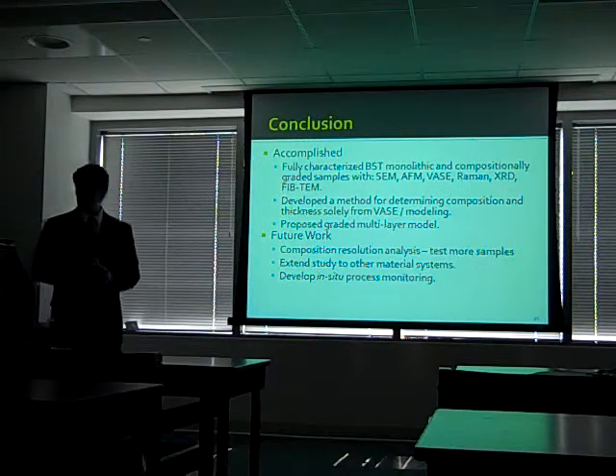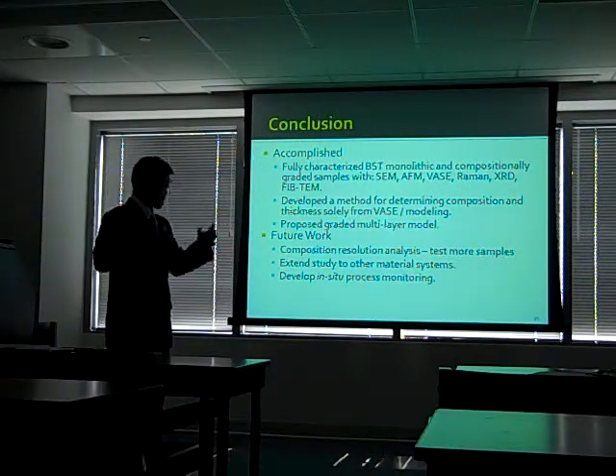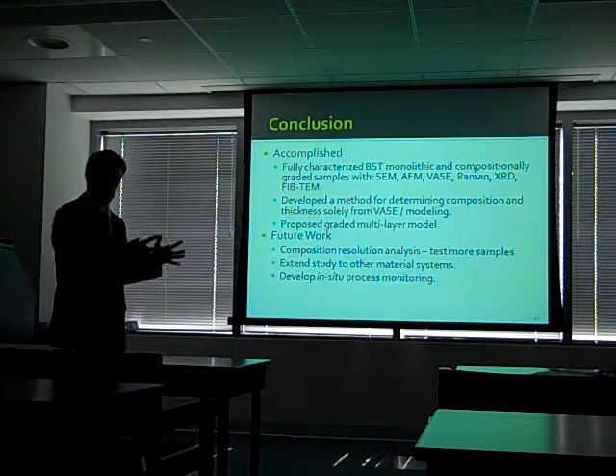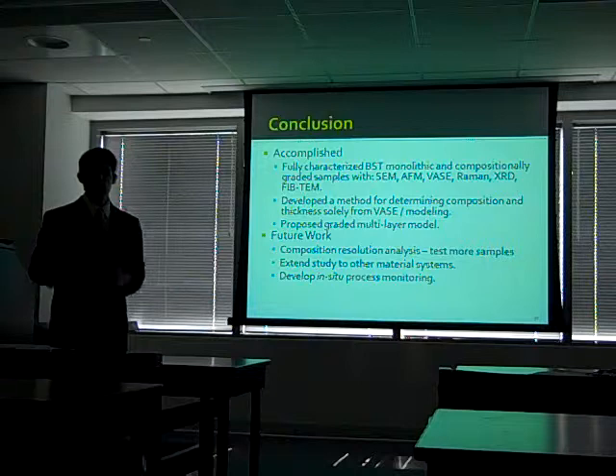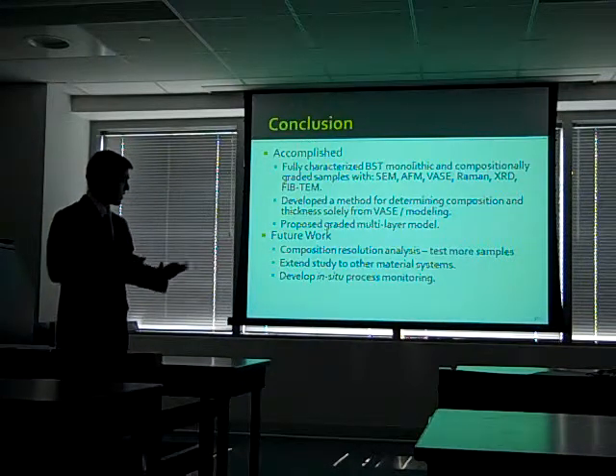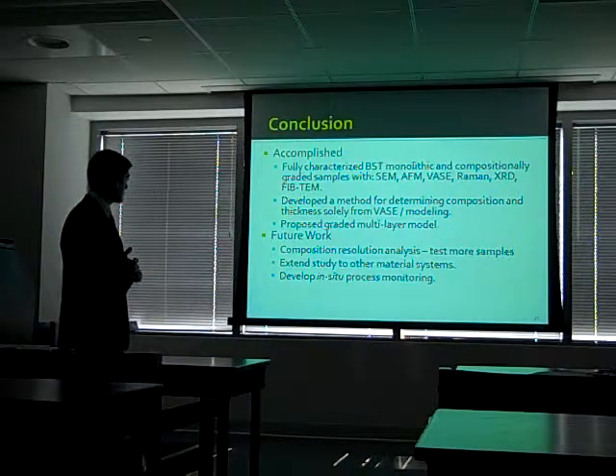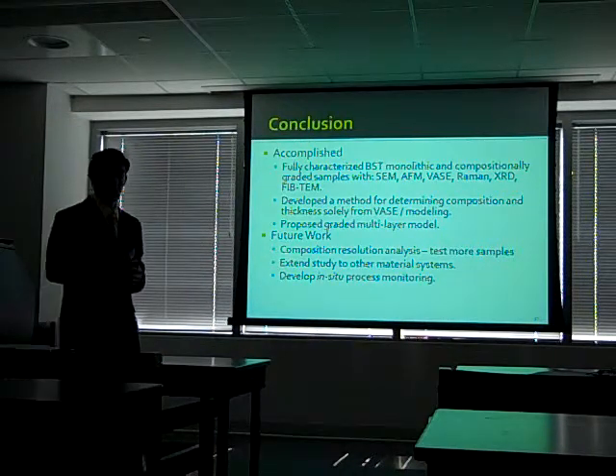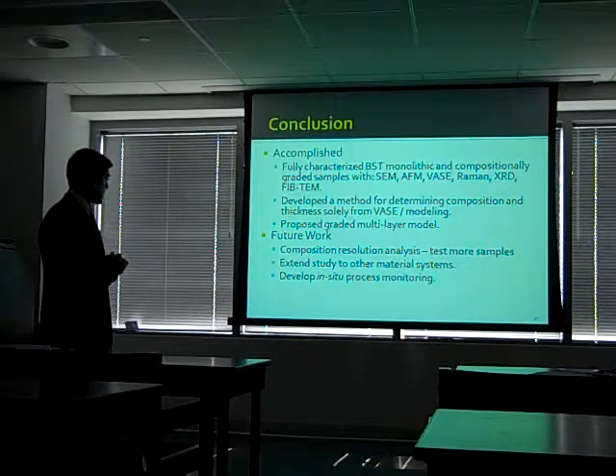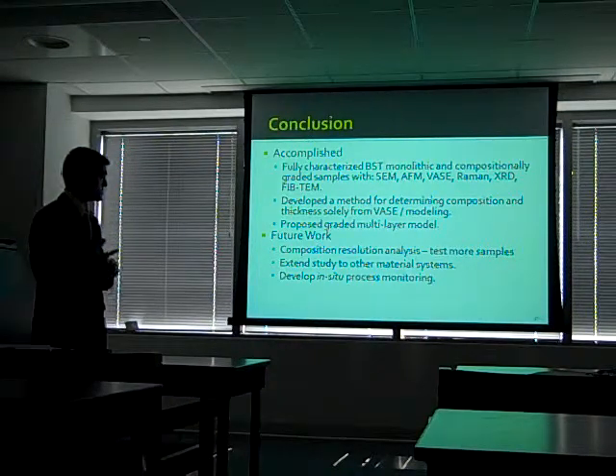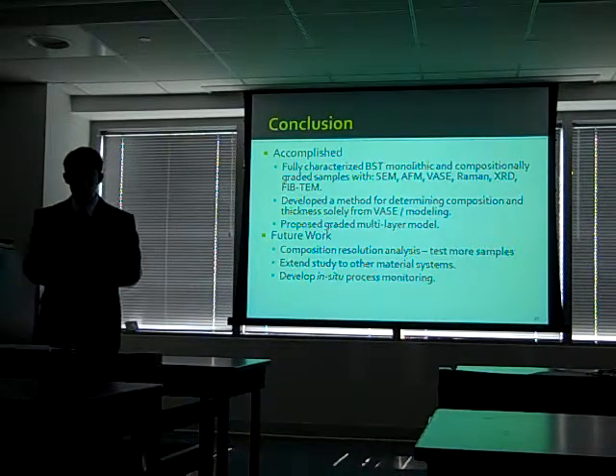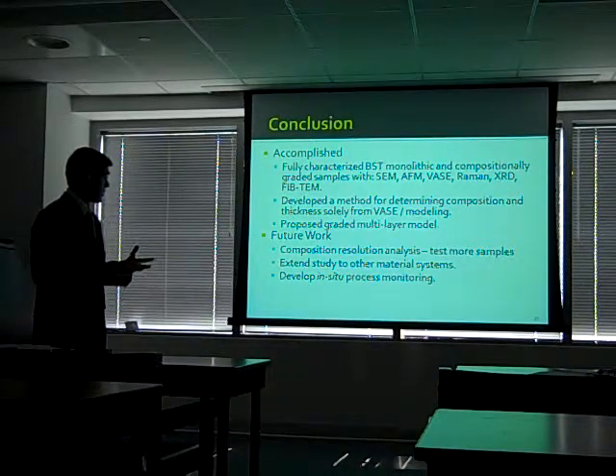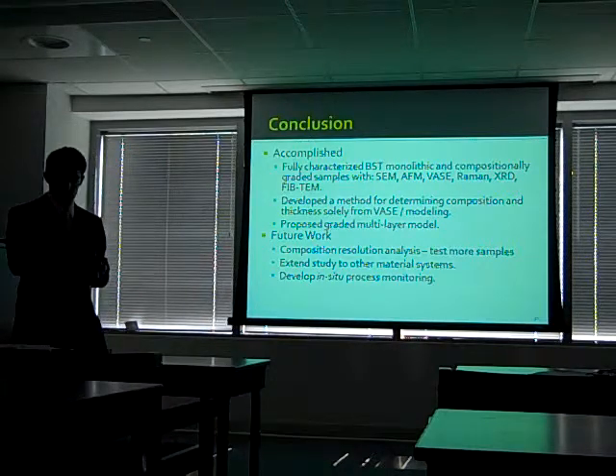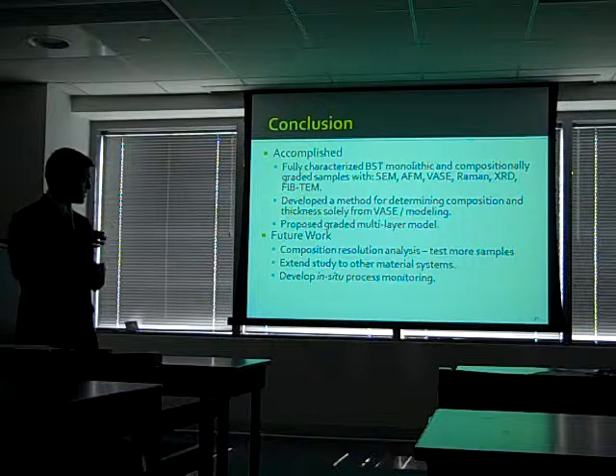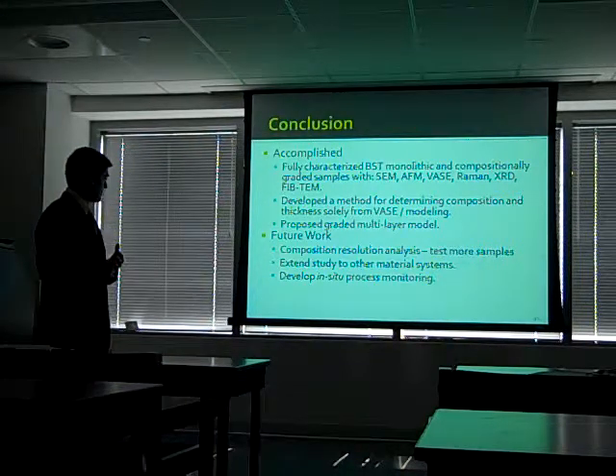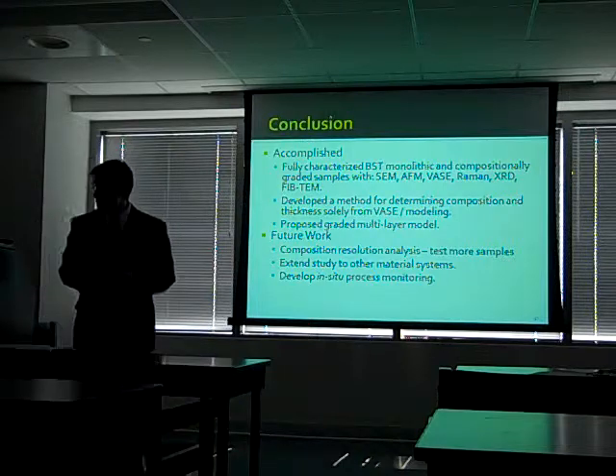Okay, so in conclusion, I have attempted to develop a framework where VASE and computer modeling can be used as an all-in-one characterization technique for thickness and composition of BST thin films. I've done that by first fully characterizing the BST monolithic samples with scanning electron microscopy, atomic force microscopy, and all the others. I've also then, from that information, developed a model and a method, which is step-by-step, for determining composition and thickness, and then I also proposed a graded multi-layer model.